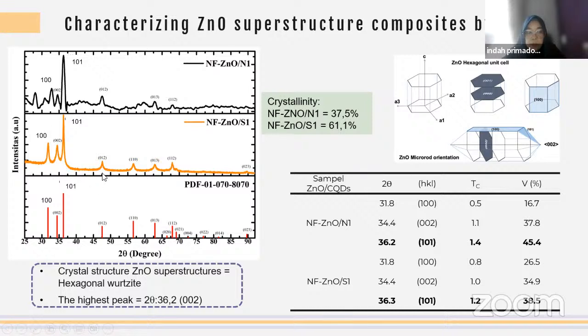And also you can see here, because our material is a composite one, it's not really sharp. Not really sharp. And also there's a hump here, so it means that there is an amorphous phase. So you can see the crystallinity is not so good actually, especially the nitrogen dope is about 37.5%, but for the SN dope is 61.1%. It's not like the previous 1D nanostructure. As I remember, the crystallinity is about 90%.